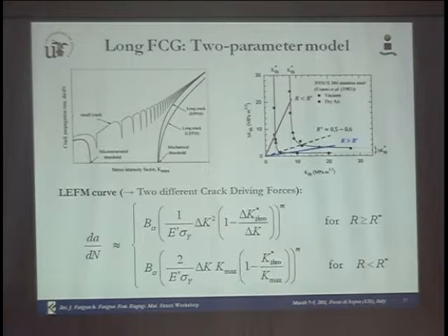Moving on to the long crack regime, we can do some mathematical simplification in this model, and we end up with the classical linear elastic fracture mechanics curve. And it's interesting that in this case we need to distinguish between two different crack driving forces depending on the range that we are working with.